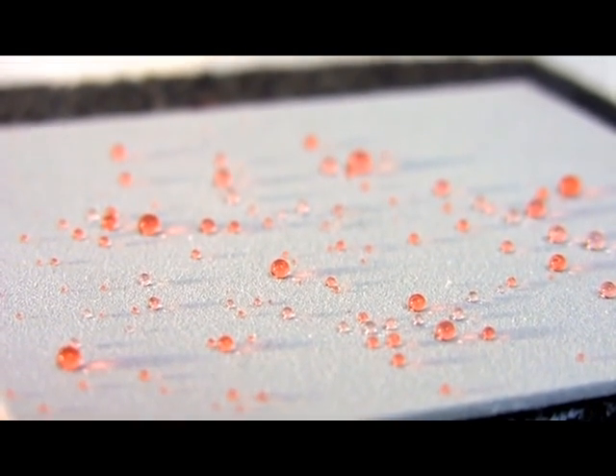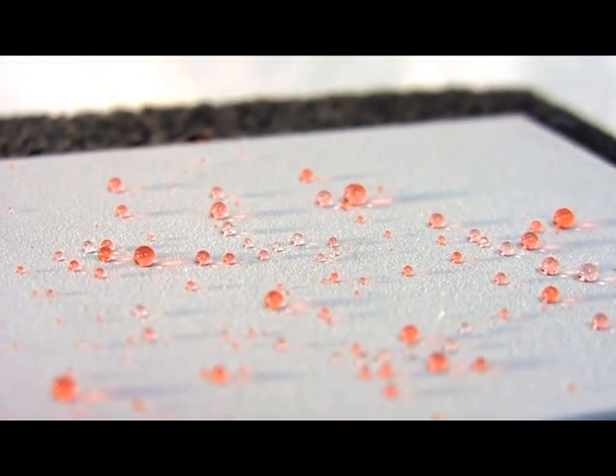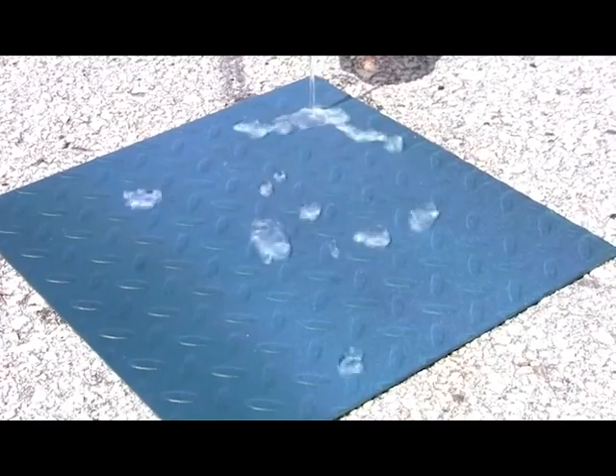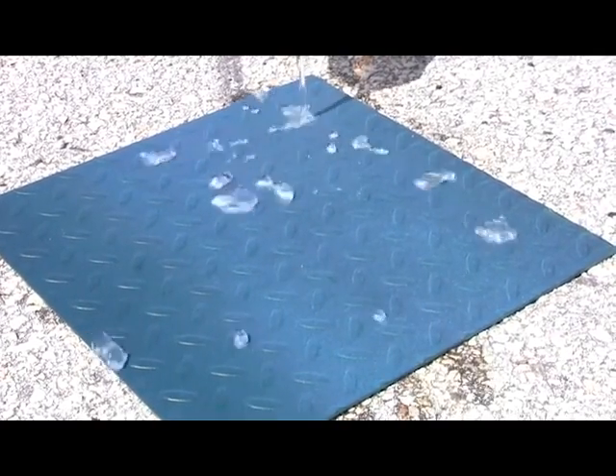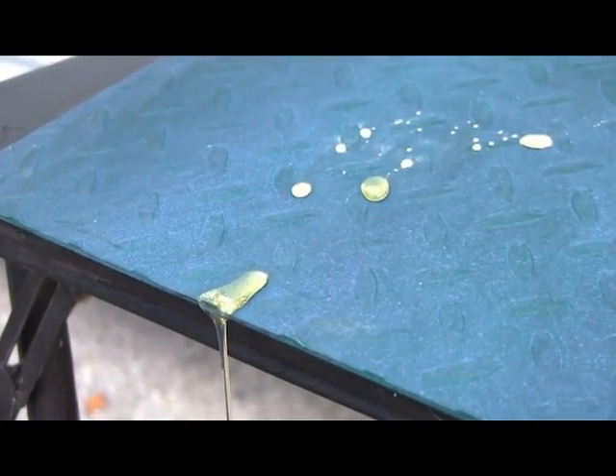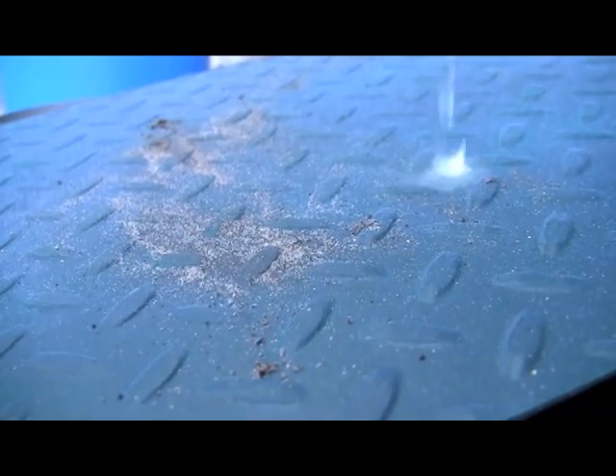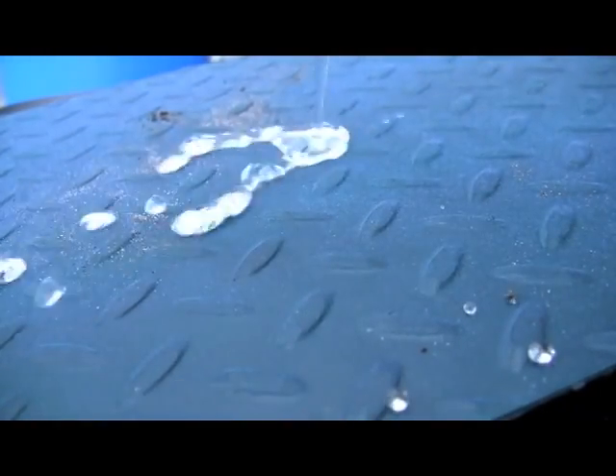Ultra Ever Dry coatings are durable coatings that exhibit super hydrophobicity and super oleophobicity. After curing, the coatings will repel water mixtures and heavy oil. Dust and dirt should rinse off easily and the surface will remain completely dry.